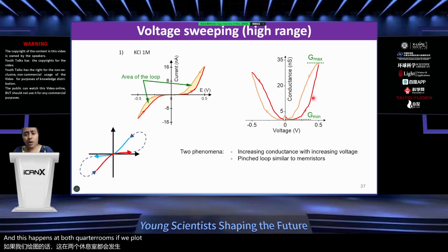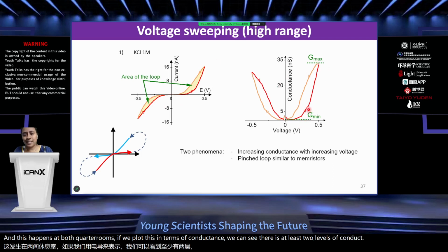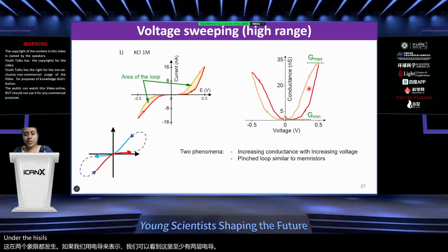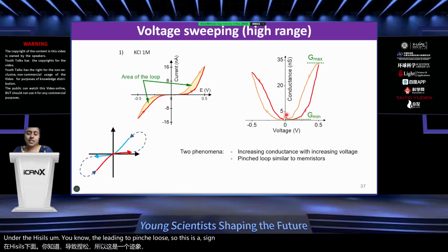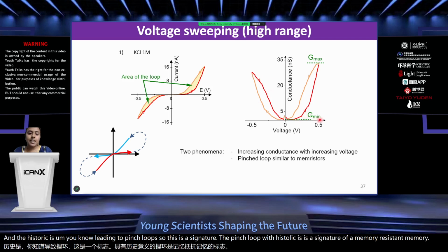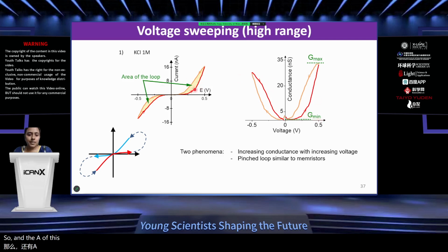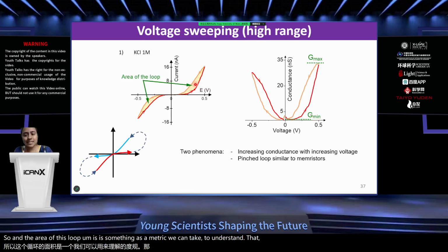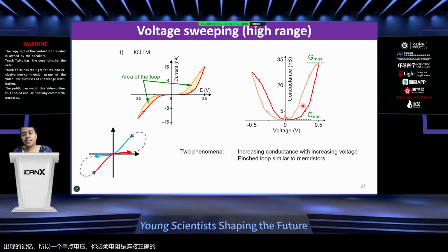If we plot this in terms of conductance, we can see there is at least 2 levels of conductance here, and the hysteresis leading to pinched loops. So this is a signature. The pinched loop with hysteresis is a signature of a memory resistor, memristor. And the area of this loop is a metric we can take to understand the emergence of the memory. So at a single point of voltage, you have 2 resistances or 2 conductances, right? So it's 2 states of memory at a single point of voltage.